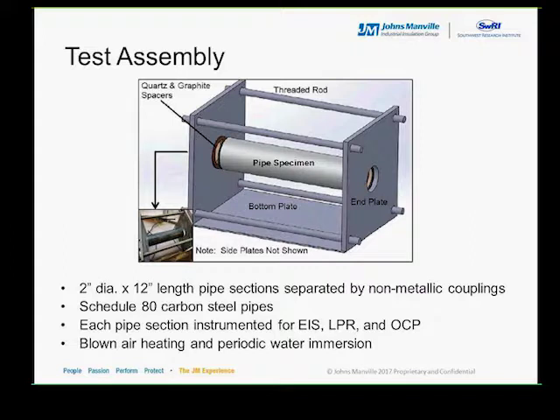The test assembly is put together following typical field installation guidelines. This test assembly is equipped with low-profile thermocouples placed on the pipe surface in contact with the insulation. This test setup can also be equipped with wetness sensors to measure the actual duration of the wet-dry cycle events.